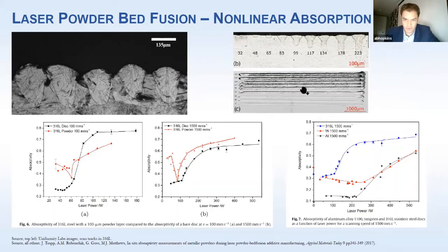This is what the tracks look like from a different perspective. Again, these are faster scans, lower power scans at the bottom, higher power scans at the same speed at the top. And then to show that the scan track shape and size is highly dependent on the metal alloy and the laser properties. You can imagine it being dependent on the laser scan speed, the spot profile and size of the laser, but it's also tremendously dependent on the metal itself, its thermal conductivity.